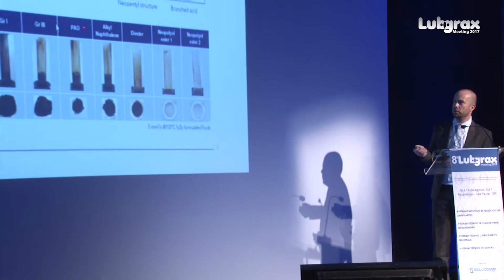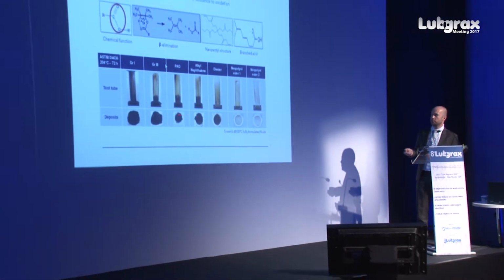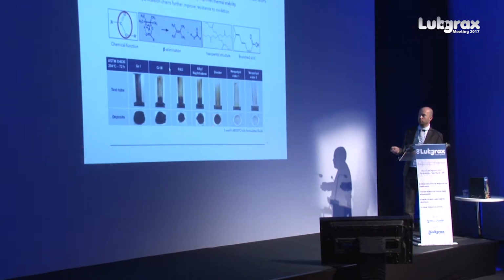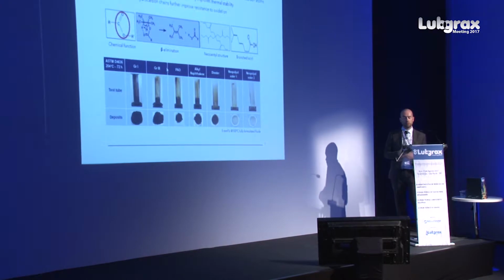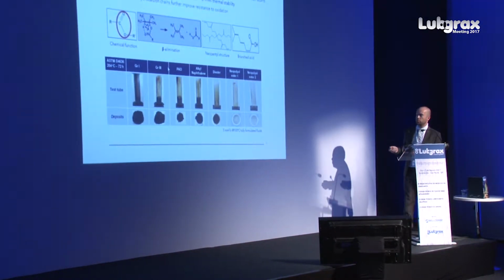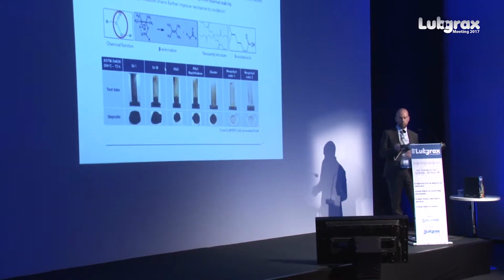Below the image is an ASTM D4636. It's an oxidation corrosion test we make a lot at NYCO. We use it only here to show the amount of deposit you can have with different base stock. It's a very severe test, we must say. Even with different mineral base stock, you have a lot of residues. Even other synthetic esters, and even commodity esters will bring you a lot of residue in your application. By choosing neopolyol ester, you will have a much cleaner surface. Here you have an example on how the raw material of esters can have an impact also. We'll detail this on the next slide with the coking propensity.